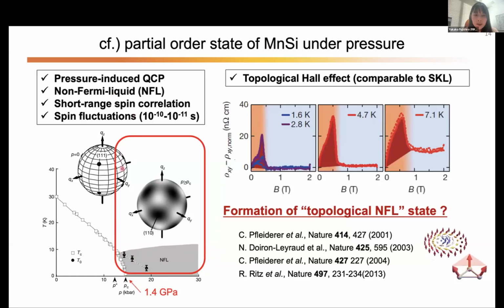And the neutron group has discovered that there is an unusual short-range spin correlation in this regime, which is strongly dominated by the spin fluctuation on a time scale of 10 to the minus 10 to 10 to the minus 11 seconds. And very interesting, they observe a topological Hall effect in this regime, which usually only appears in the magnetic skyrmion phase. So from these results, they have named this region a topological non-Fermi liquid state, and they speculate that the liquid-like state of the magnetic skyrmion is actually formed in this region.